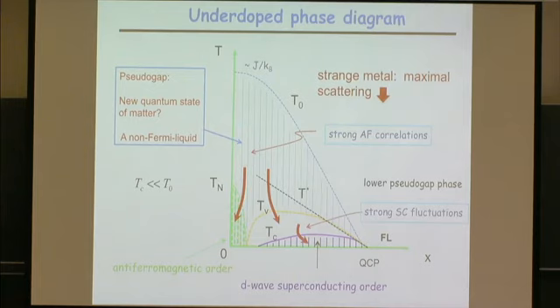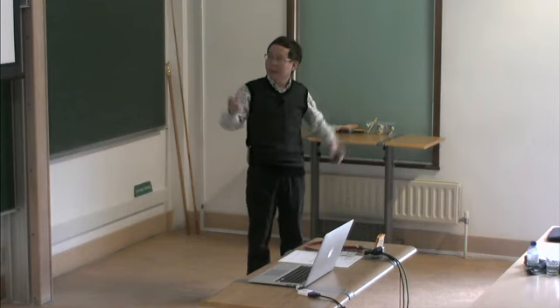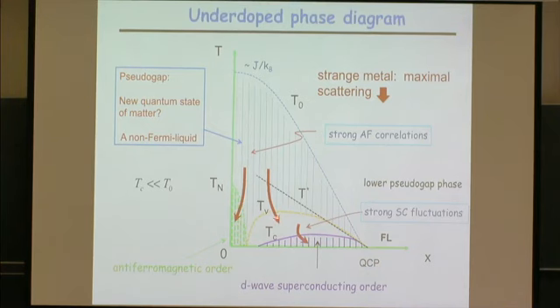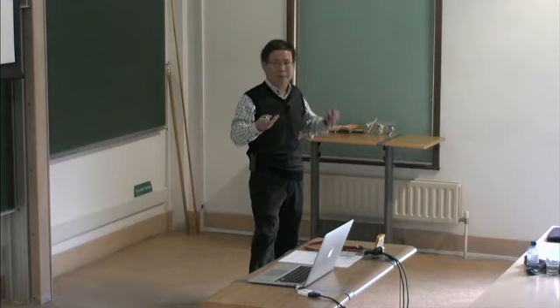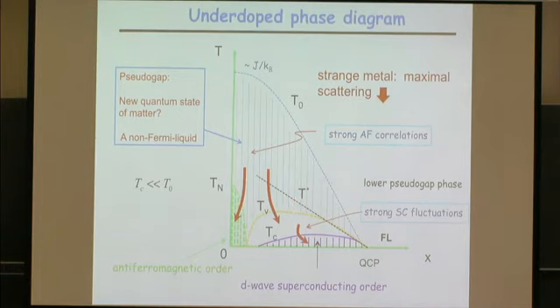But if the doping concentration is higher, you find that the strong antiferromagnetic fluctuation will stop developing long-range order at some low temperature. Instead, superconducting fluctuation will come out. Eventually, it goes into the superconducting state. And this T0 we have seen in the uniform susceptibility.